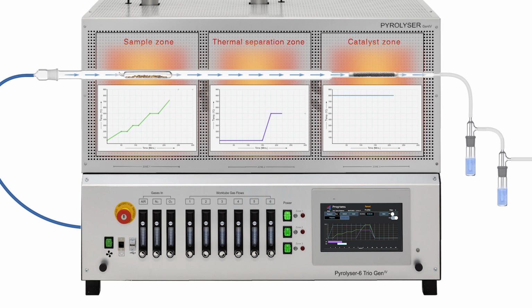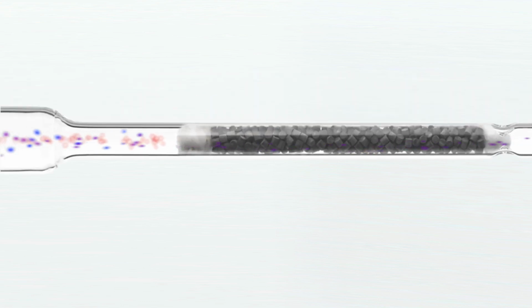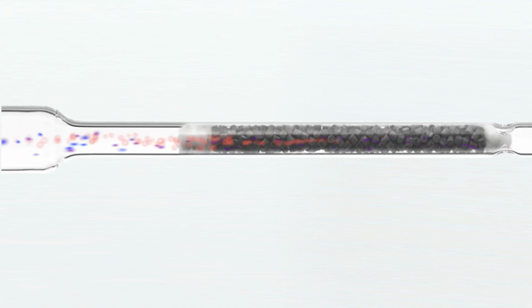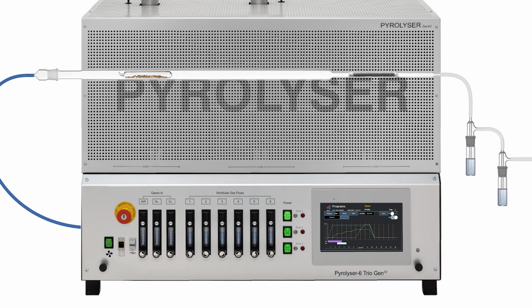The sample zone is now ramped to 900 degrees C to ensure the continued oxidation and opening out of refractory materials. All combustion products liberated over the temperature range 50 to 900 degrees Celsius are fully oxidized after passing through the platinum alumina catalyst bed. By 900 degrees C, all tritium and carbon-14 will have been liberated and transferred to the external traps. These oxidized products, tritiated water and carbon-14 labeled carbon dioxide, collect in their own external bubbler traps.